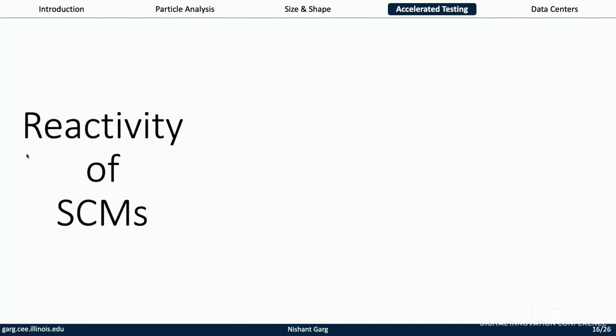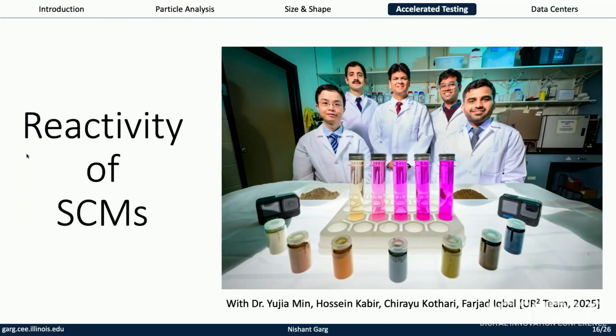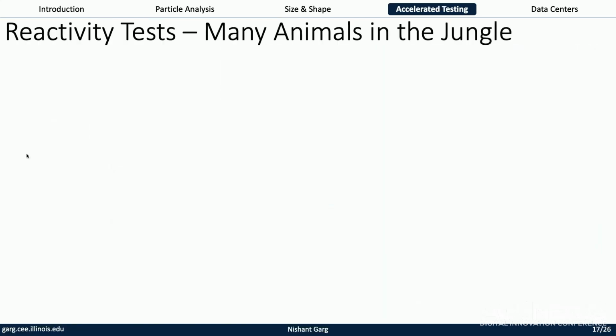So that's the question we started to ask a couple of years ago, and the first thing we looked at was the reactivity of supplementary cementitious materials, such as fly ash, slag, natural pozzolans, and things such as calcined clays. So this was the work done by a team of students here. We came up with a neat, low-cost method using cameras to detect concentrations of aluminum and silicon in these liquids, which would typically require an expensive piece of equipment like an ICP, which is a few $100K, and this is all done with a $50 camera, right?